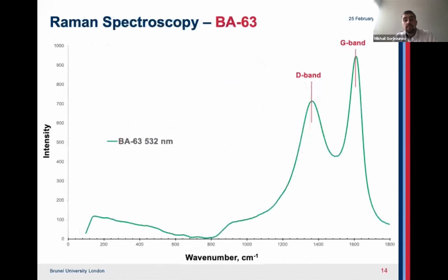We also utilized Raman spectroscopy as a complementary technique to the FTIR. The D and the G bands of carbon are easily identifiable from the spectrum, leading to the conclusion that the sp2 hybridization state of the carbon is prevalent over the sp3 hybridization state.